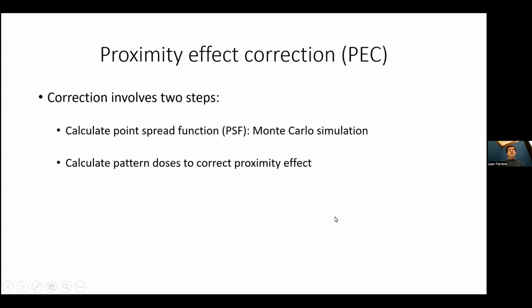This process that we do to invert the scattering is called proximity effect correction, and it involves two steps. The first step is to calculate the point spread function, which is done with a Monte Carlo simulation, and that's what the plots that I showed you before were done with, a Monte Carlo simulator. Once you know the point spread function, you can calculate the convolution of this PSF, and then do an inversion, which, like I said, is not an easy problem because of the background being always present.